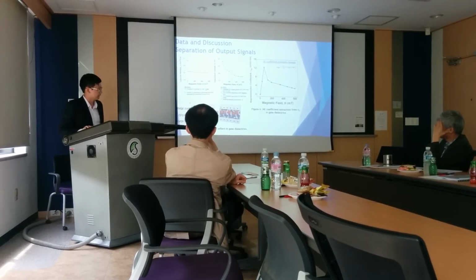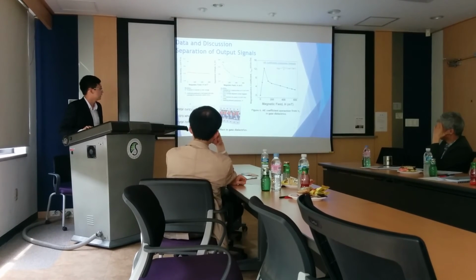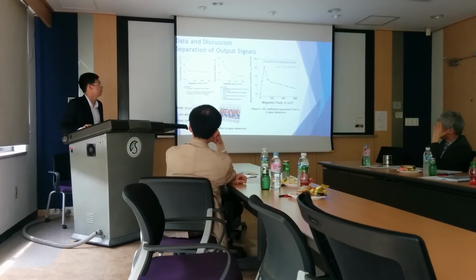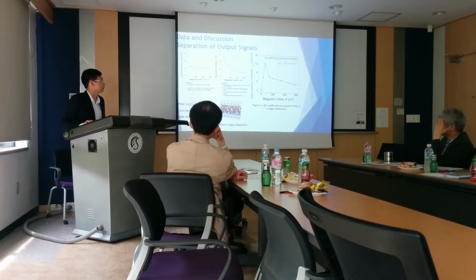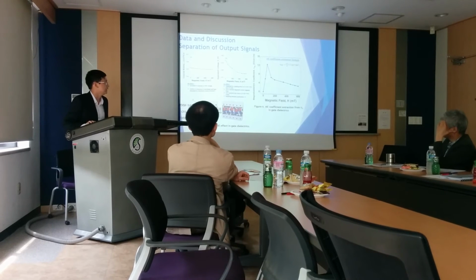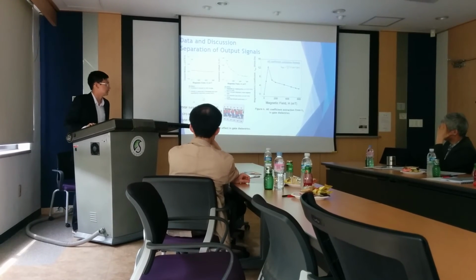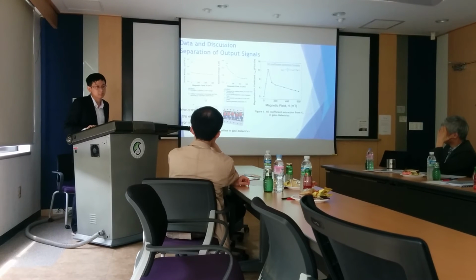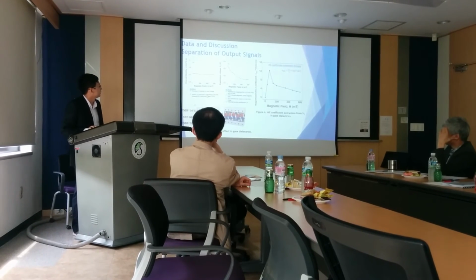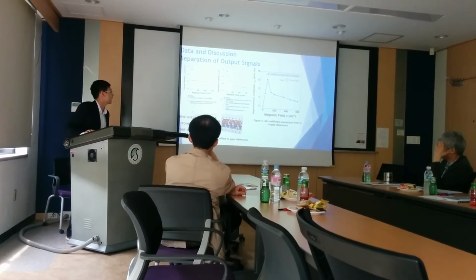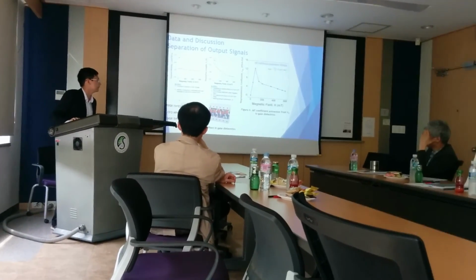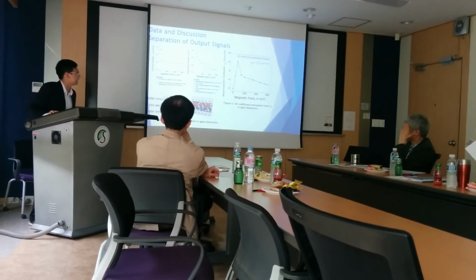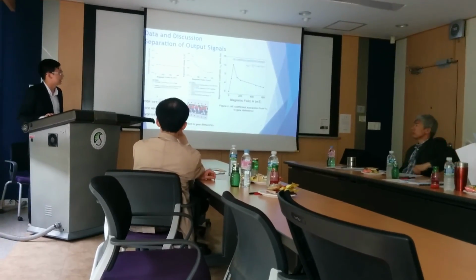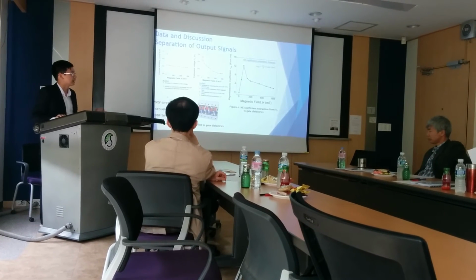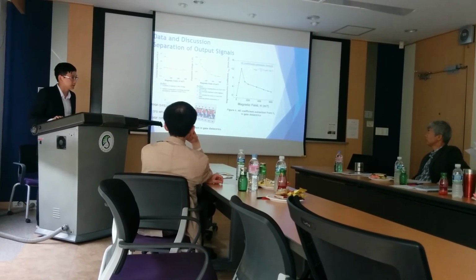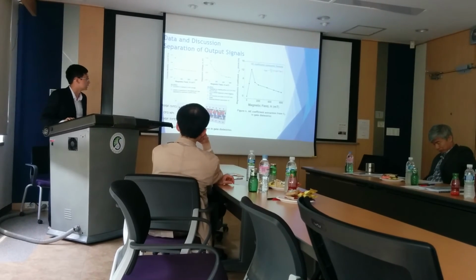When the magnetic field is applied to the MEOFET, the carriers in the pentacene channel will be bent to each side, and the mobility will decrease. Then it will saturate because of the maximum Lorentz force. On the other hand, in the case of the gate dielectric, we attribute it to the magnetoelectric effect happening by the coupling between the PVDF-TrFE and cobalt ferrite CFO nanoparticles.